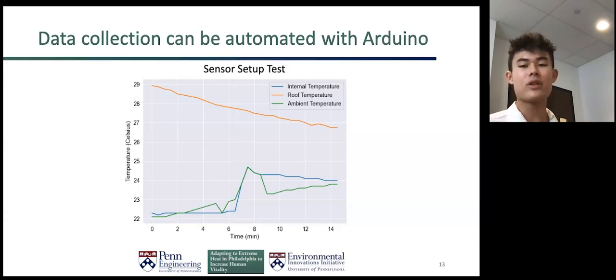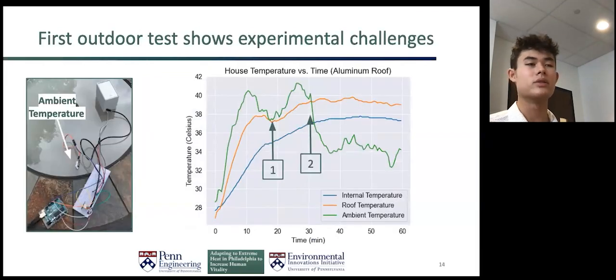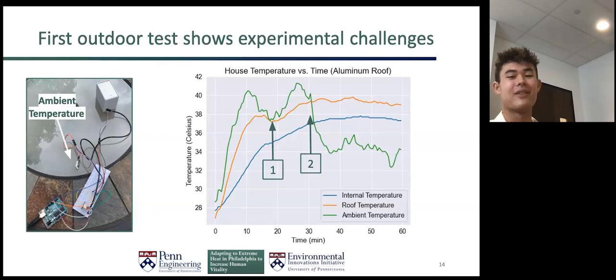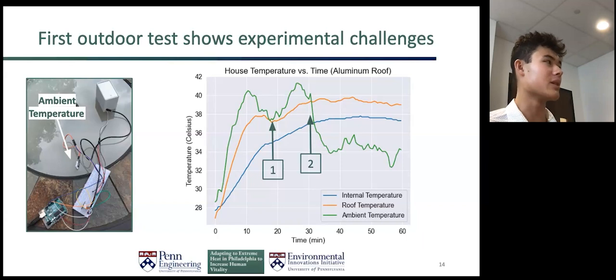And then after I confirmed that the sensors were working, I did an initial test outside using an uncoated aluminum substrate. And I learned a few more things from this. First, arrow 1 shows a sudden drop in roof and ambient temperature. And that was because a cloud passed overhead. And it was cool to see how profound of an effect that could have. I didn't expect that it would affect the roof temperature that dramatically, that quickly, but it's good to know.